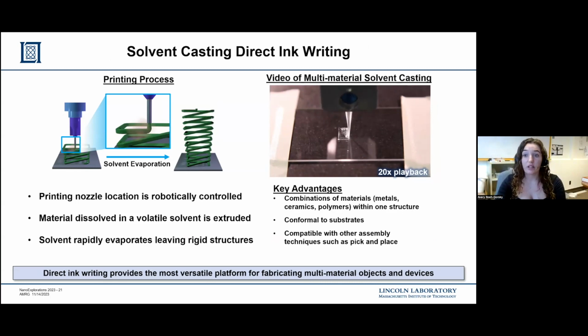Specifically within material extrusion, we are using solvent casting direct ink writing. As you can see from the video, it is a robotically controlled arm using CNC code that prints our ink. Our ink is our material dissolved in a volatile solvent. So basically, once it's deposited onto the build plate, the solvent rapidly evaporates out, leaving behind a rigid structure.